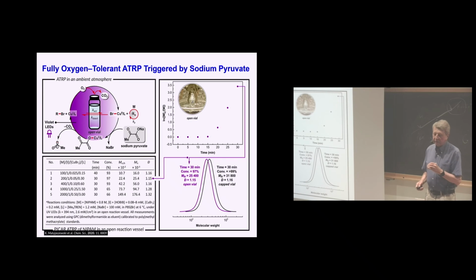And in fact, you could do it with light. I mentioned to you before that this bromidophilicity, or fixing bromide on copper 2, is reversible. And now you have another anion, you have a pyruvate anion, and you form copper 2 pyruvate, which is light sensitive. And it's enough to irradiate it with light, reduce copper 2 to copper 1, so you regenerate activators, produce pyruvate radicals, which very quickly decarboxylate, form acyl radicals, which are not efficient initiators. So now you can work in a completely open-to-air atmosphere.